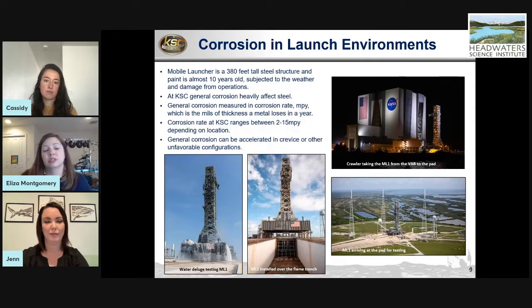When we measure corrosion rates, the metric we use is called mils per year, which means the mils of thickness that you lose from a surface in a year. It ranges from around 2 at the launch pad to 15 at our test site, depending on the location. And these are some examples of different conditions.